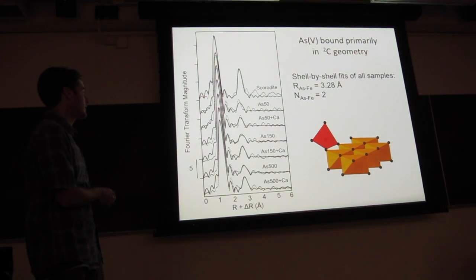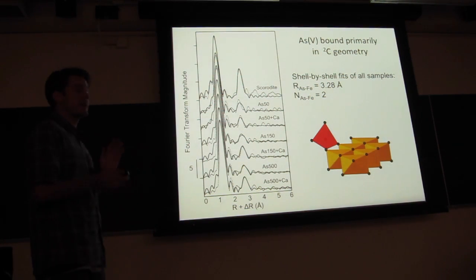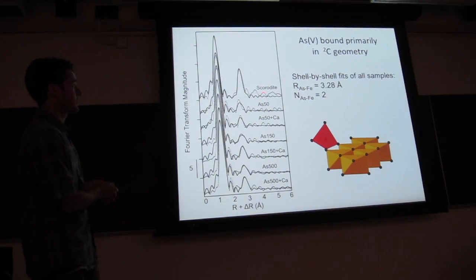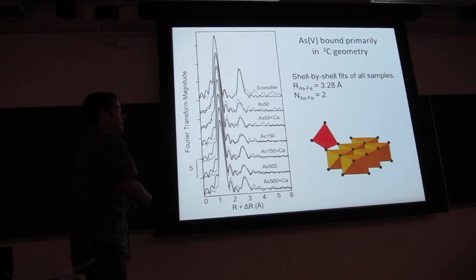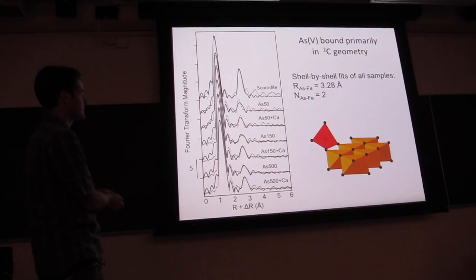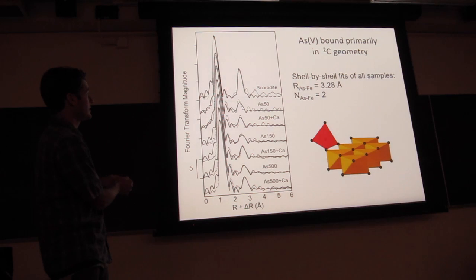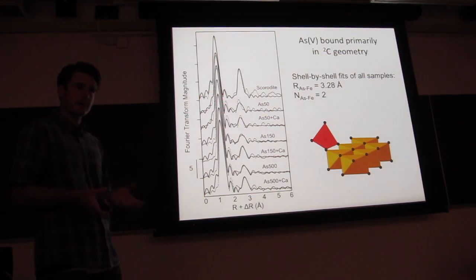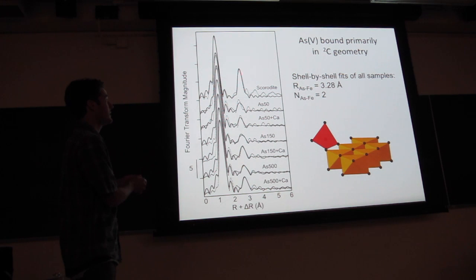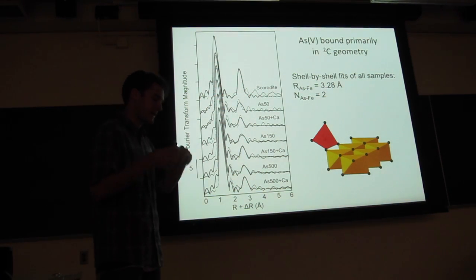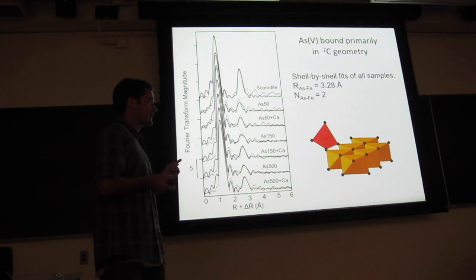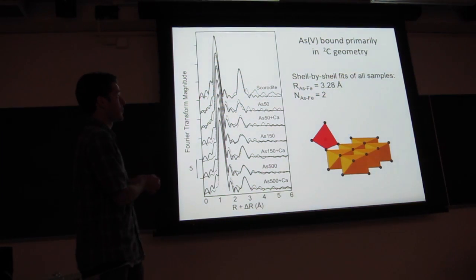So here we have, again, a series of peaks that correspond to the interatomic distance between atoms. And at the very top, I'm showing scorodite. And scorodite is an iron arsenic mineral. And the first peak here corresponds to arsenic oxygen. And you can see that this peak in scorodite is similar to the peak in our samples. And we would expect that for arsenic 5. But the second shell peak, this peak here, in scorodite, the position is shifted. And of course, the amplitude is much higher. And this is because in scorodite, arsenic is actually incorporated into a crystal structure. And so arsenic sees much more iron atoms in a crystal than it does when it's adsorbed to something. And so that explains why you see a much larger amplitude here.